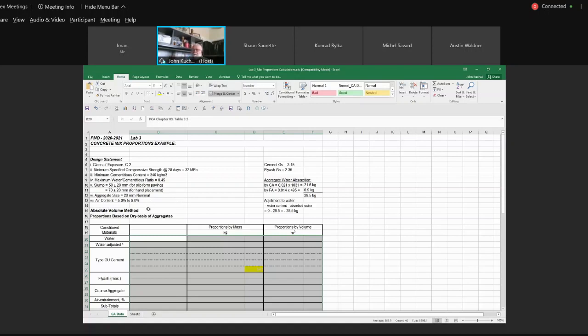He may kill it. He may add water all the time. He may overwork it. He may not place it properly. That's a construction. It's not the concrete's fault. It's the contractor's fault. Okay. So we're looking at the maximum water cement ratio, 0.45. Typically, you don't have to specify that. City didn't even have to specify that one because they specify C2. You specify C2, you automatically specify category 1 for air. You automatically specify water cement ratio. What the city did, no big deal.